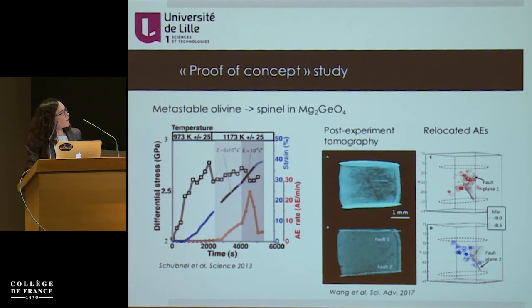So, of course, you need to prove that this is coming from the sample. So there was some post-experimental tomography on the sample, and that highlighted that we have some cross-cutting faults within the recovered samples. And recently, some people using double difference techniques relocated the acoustic emissions, and you can see that the location of these acoustic events within the sample correlate pretty well with the faults that cross-cut the sample.